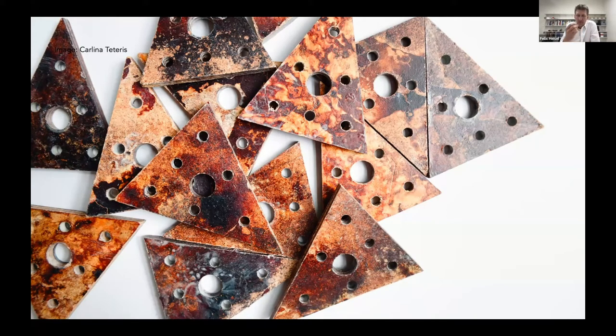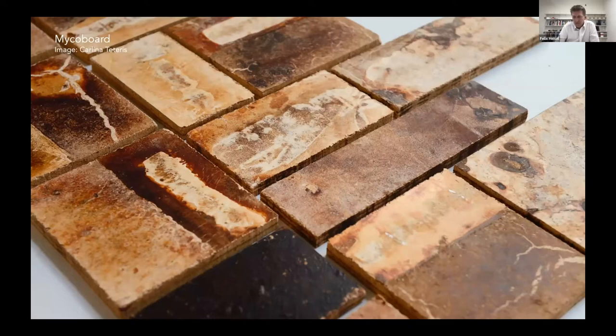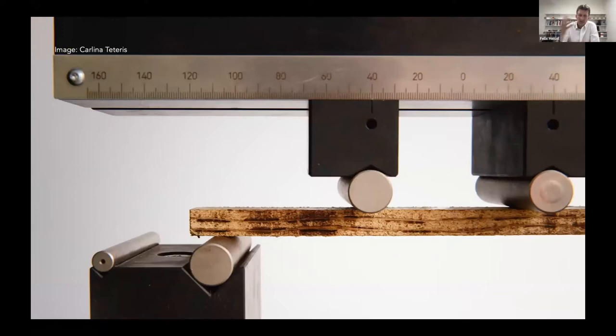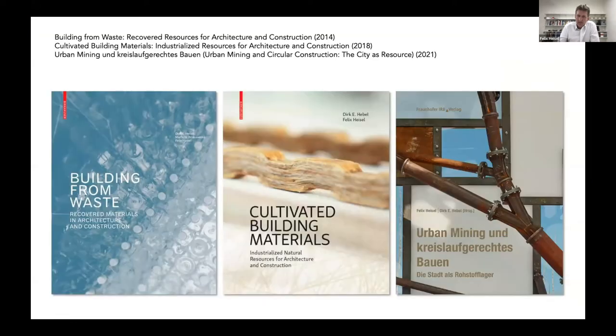What you see now is a mycelium-bound high-density board — only mycelium in here. Over time we replaced the bamboo with pure mycelium. These boards achieve strengths similar to particle boards that can be used in structural applications. The material is pure mycelium, going back to the circularity goal of the whole research — it is completely compostable. It is a purely biological material that can go back into the cycle.